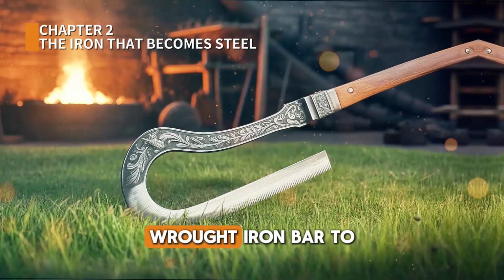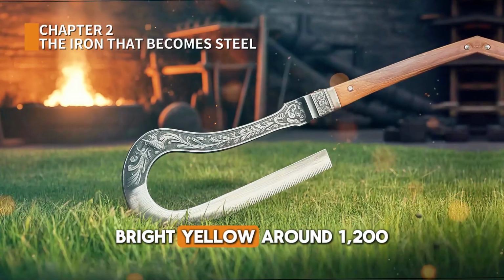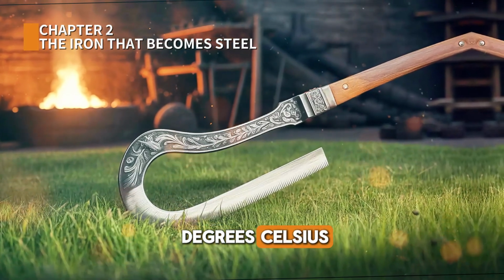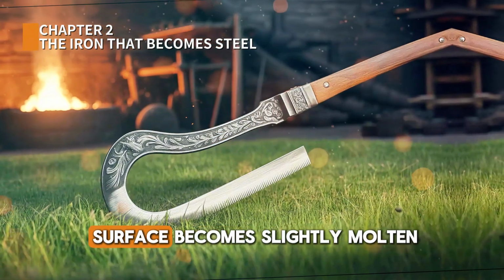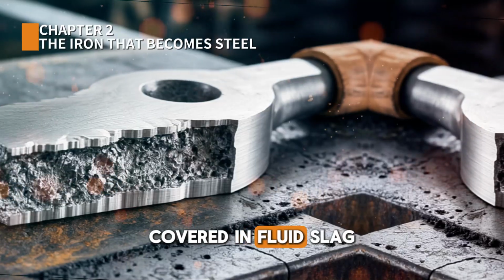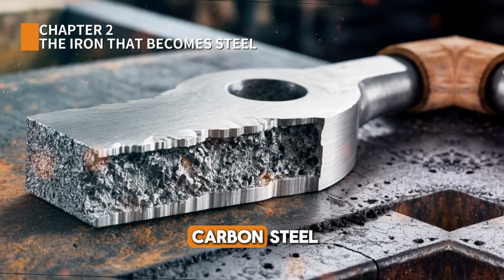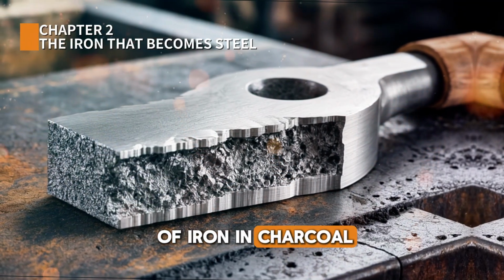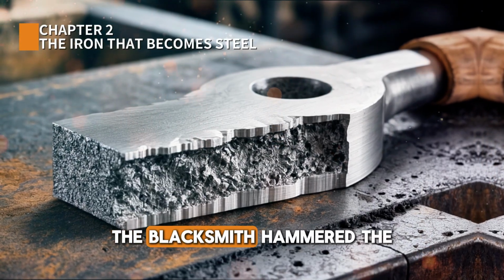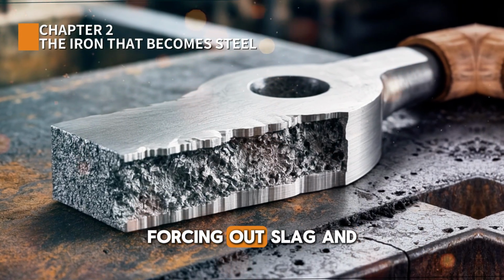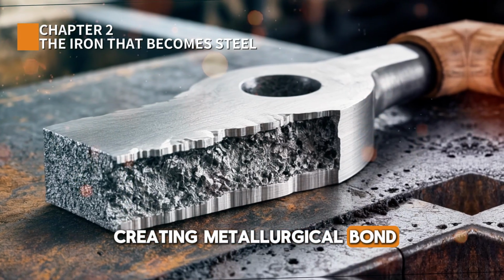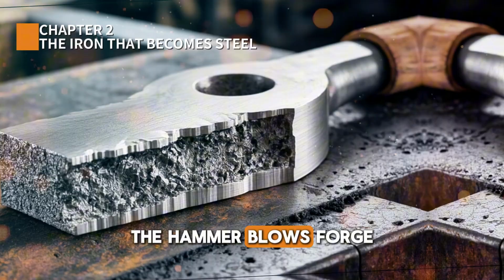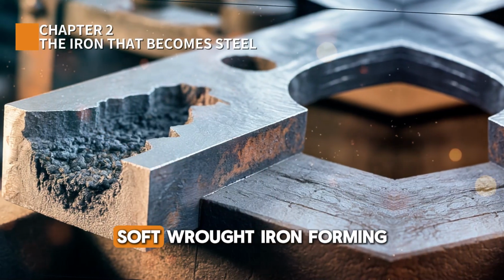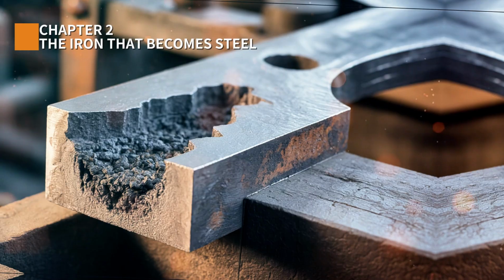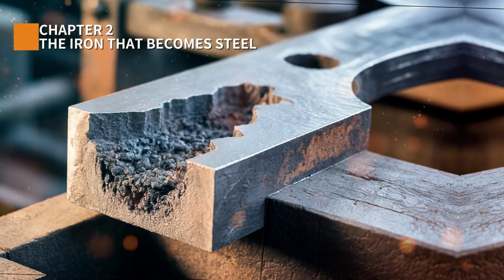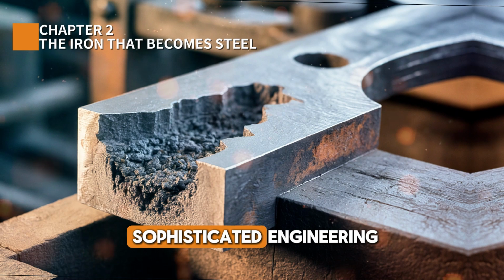The blacksmith heated a wrought iron bar to welding temperature, bright yellow, around 1,200 degrees Celsius. At this temperature, the surface becomes slightly molten, covered in fluid slag. A strip of high-carbon steel, produced by prolonged heating of iron in charcoal, was placed on this hot surface. The blacksmith hammered the two pieces together, forcing out slag and creating a metallurgical bond at the molecular level. The hammer blows forged the materials into a single piece, soft wrought iron forming the blade's body, hard steel forming the cutting edge. This composite structure was sophisticated engineering.